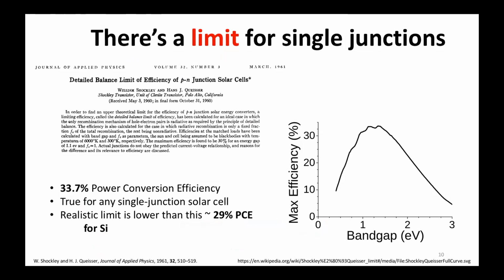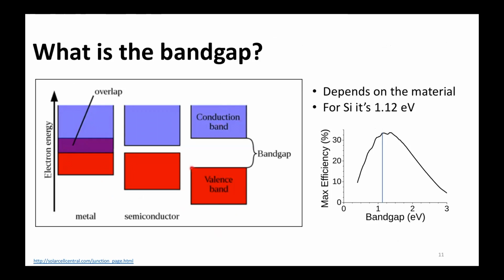You heard something about the Shockley-Queisser limit. So for silicon, it's 29. The real theoretical limit is 33.7. And for silicon, of course, the band gap is basically the energy difference between the valence band and the conduction band. That is how you can look at it. For a single junction, we have a certain limit. For a tandem cell, the limit is different. And it depends on what you combine.